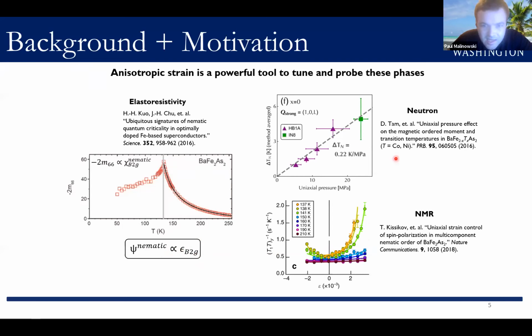Furthermore, the strong magnetoelastic coupling in these materials implies that anisotropic strain can also act to tune the antiferromagnetic phase. So for example, work from the group of Pengcheng Dai, who's one of our great organizers, demonstrated that the Néel temperature is increased by uniaxial stress. And even more recently, NMR measurements from Nick Curro's group directly show that anisotropic strain enhances spin fluctuations above TN. So with these sorts of ideas in mind, the basic idea of our work is to use anisotropic strain to tune the magnetic and nematic phases and then see how the superconducting state responds.